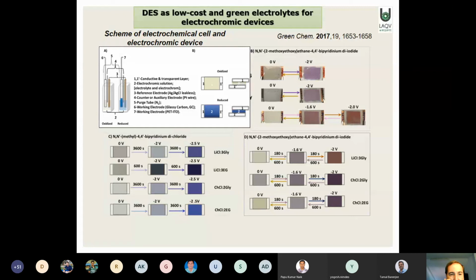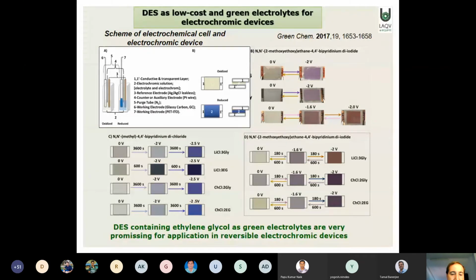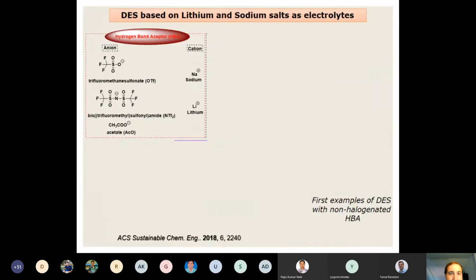After that, here you can see that it's possible to change the colorations. It's possible to check different kinds of approaches in electrochromism, and the deep eutectic solvents containing ethylene glycol as green electrolytes are very promising for this kind of application in reversible electrochromic devices.